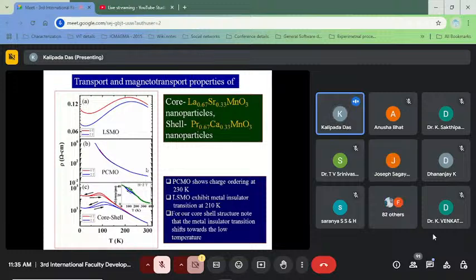However, in the case of PCMO, the parent compound, it shows charge ordering around 230 Kelvin, and then a sharp increase in resistivity, reaching a value beyond the measurement range of our instrument. But in the case of the core-shell type sample, when we placed some LSMO nanoparticles within the PCMO matrix, the metal insulator transition shifts towards low temperature and the resistivity value is reduced with respect to the parent PCMO compound. And charge ordering still appears around 230 Kelvin.